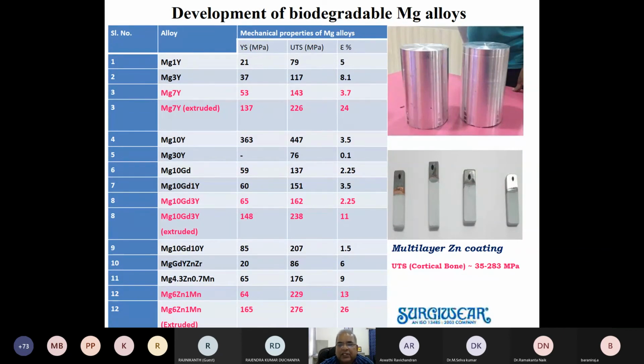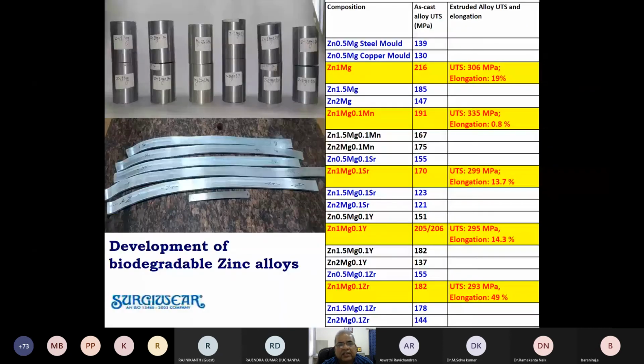They are good for papers, but they are not working on the industrial scale. So we try to develop a multi-layer zinc coating through a novel route. It's an electroplating process, which was itself a challenge. We got coating zinc on the magnesium, a lot of electrochemical issues. What we could do that. And again, this process we are giving to Surgiwear, it's a collaborative process.